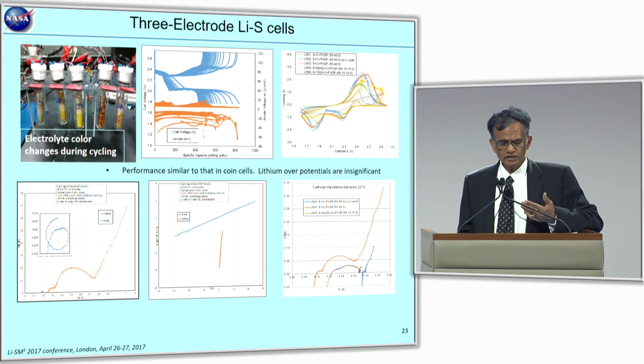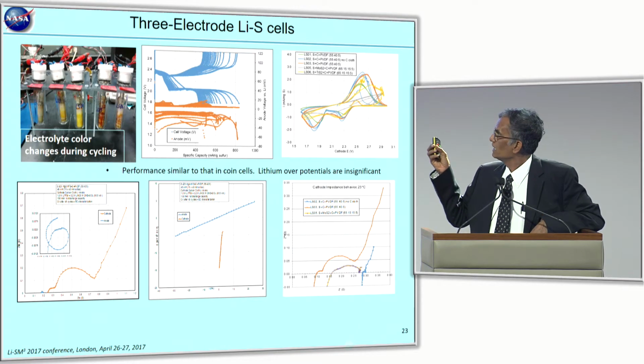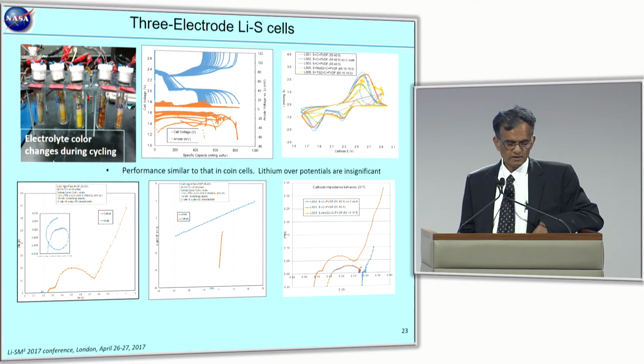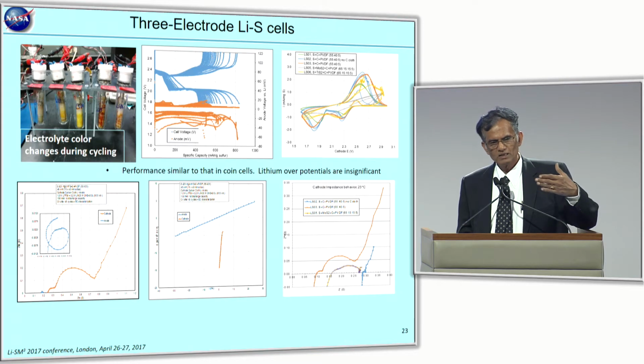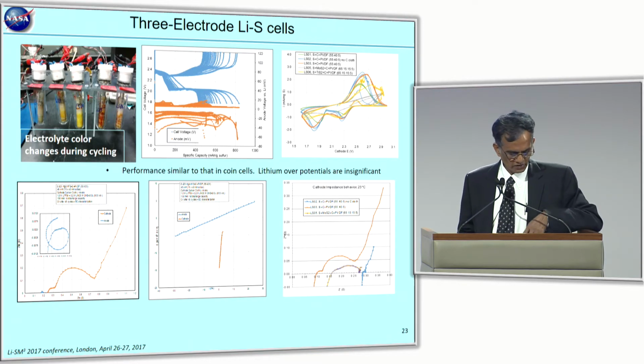And then of late, we started making bigger cells, like glass 3 electrode cells. These are cells with about 150 milliamp hour. These cells let us look not only at the changes in the electrolyte color as it cycles, but also at the individual electrode characteristics. On the top middle, you can see the polarization is coming mostly from the sulfur cathode, a lot of hysteresis, as opposed to sulfur lithium, which does not show any such.